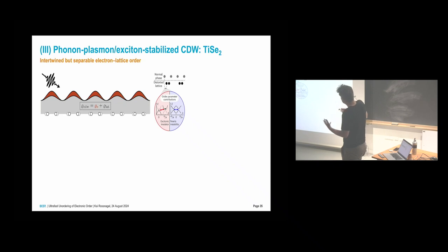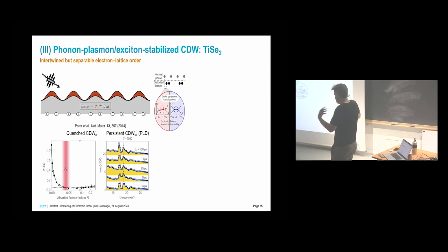Okay, and then type 3 is finally this excitonic type instability, where so far everything was tied to the lattice charge density. Here now we can really have the separation where we also have an electron charge density, and where in principle in the time domain we can split these things. So people have also illustrated it in this way, so that we have an order parameter, and this has two contributions, one coming from this excitonic insulator instability and one from the Peierls instability. And this has also been demonstrated already in terahertz spectroscopy.